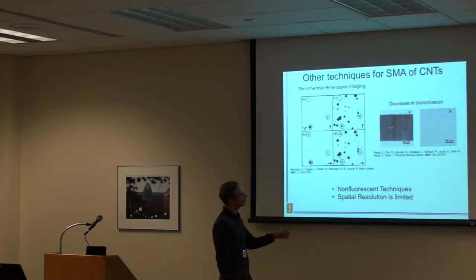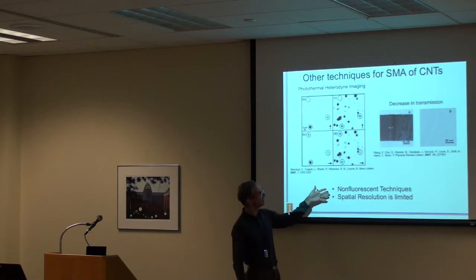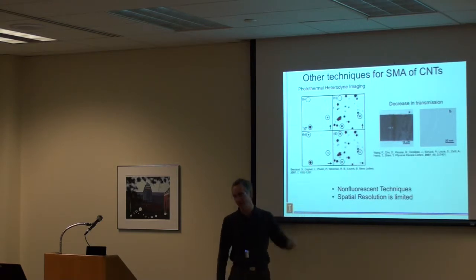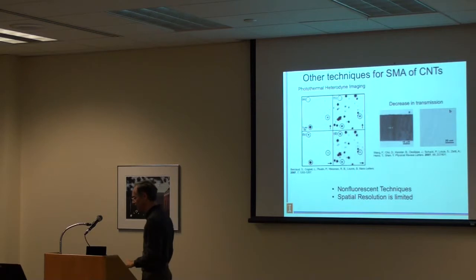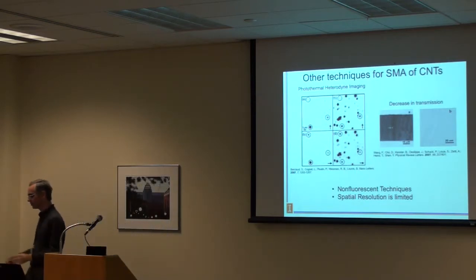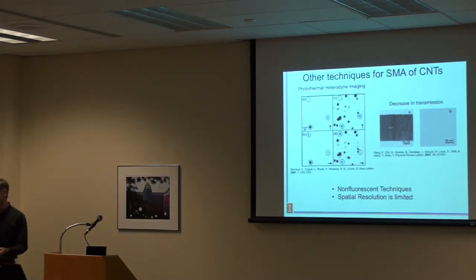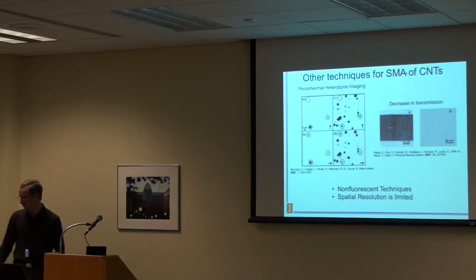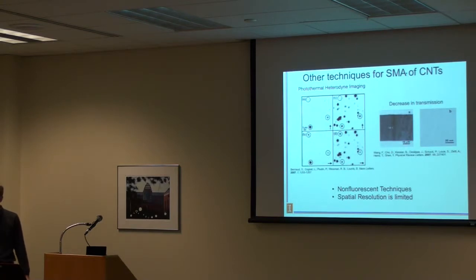And so the problem, though, with these methods here is that your spatial resolution is limited, and I'll come back to that at the very end of my talk. You basically don't get any significant spatial resolution, whereas by our method, we get angstrom-level resolution on the molecule. We can tell one part of the molecule, like that nanotube I showed you, from a different part that's adjacent to it, just less than a nanometer away. And so that's what I mean by our ability to actually do submolecular resolution spatially, single molecule absorption spectroscopy.